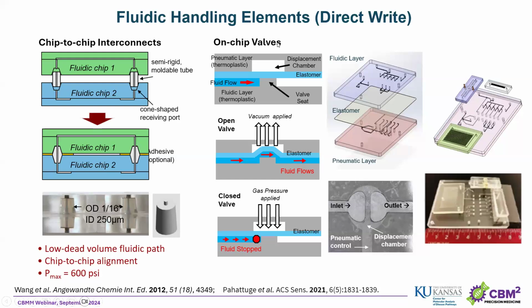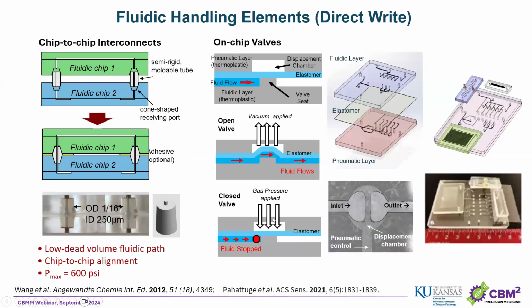The other way is to make the on-chip valves. This is a combination lamination of different materials. So you will have a bottom chip fluidic layer, and then we may have the pneumatic layer on the top with some elastomeric or thermoplastic elastomer on the top. And as we apply vacuum, we pull this elastomer, opening the path for the fluid flow, or we apply pressure, we're closing the valve. And this is the top view of one of those valves machined directly in plastic.